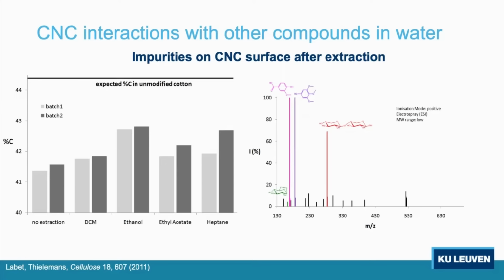So basically these are things that you get from your acid hydrolysis. So if you want to do surface modification, you have to do Soxhlet extractions to purify surfaces. Yeah, it actually makes sense once you know it, but like 10 years ago, nobody purified their surfaces before trying to modify. Now, where does this difference come from?